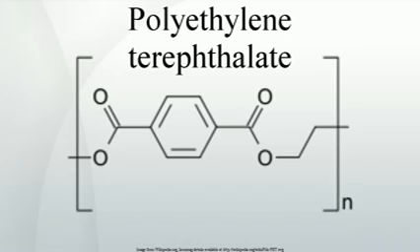Dimethyl terephthalate process. In the dimethyl terephthalate process, this compound and excess ethylene glycol are reacted in the melt at 150 to 200 °C with a basic catalyst. Methanol, CH3OH, is removed by distillation to drive the reaction forward. Excess ethylene glycol is distilled off at higher temperature with the aid of vacuum. The second transesterification step proceeds at 270 to 280 °C, with continuous distillation of ethylene glycol as well. The reactions are idealized as follows.